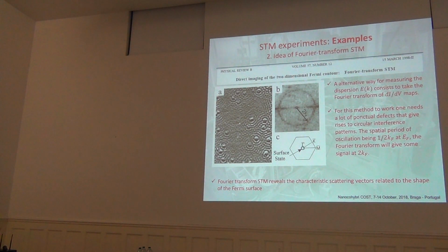And that gives you immediately an idea, not immediately because now we are in 98, an idea of, okay, so imagine I have a completely perfect copper plane, okay? In such a case, it is very difficult to get atomic resolution because my electronic waves are just planar waves. So the amplitude of atomic resolution, the modulation, is extremely tiny. Typically, it is 0.01 angstrom. It is possible to observe, and we do, but it's difficult, okay?